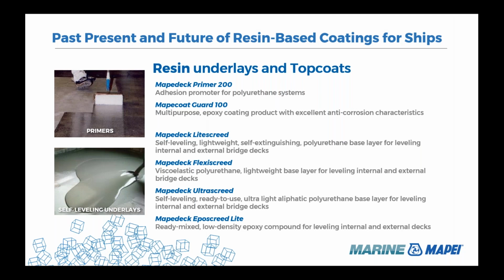Now remember that these resin systems really look a lot better if we address the issues with the steel deck. Remember back when we talked about the oil-based paint and seeing the seams and the welds and the rise and fall in the deck? Now we use certain underlayments to fill the deck and smooth the deck, and we covered these in a previous presentation, but I'll quickly go over them. We've got the Mapedeck Primer 200, which is a standard primer for our polyurethane decking materials, including our underlayments. And we have the Mapecoat Guard 100 product, which is an anti-corrosion primer that can be used with cement-based underlayments, as well as polyurethane and epoxy materials.